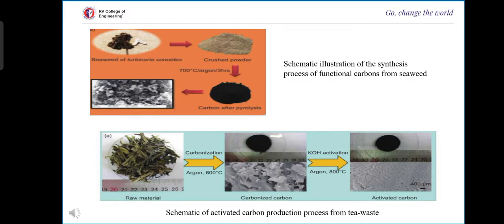Here are some of the pictures showing how activated carbon and functional carbon are made from biomass. The first picture shows how functional carbon is synthesized from seaweed. Here the seaweed is crushed into powder and heated up to 700 degrees Celsius in the presence of argon for 3 hours, giving the carbon after pyrolysis, as you can see in the picture.